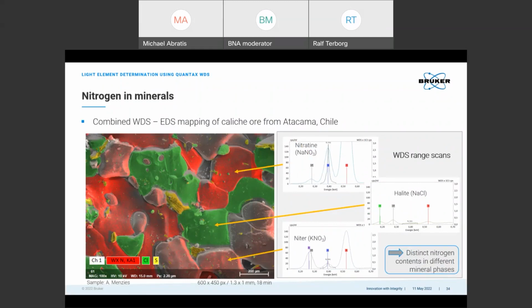There are two principal types of WDS on the market. The classical one uses a so-called Rowland circle and no optic. In such a system, the solid angle is small. That means a lot of the X-rays get lost for analysis. In contrast to that, a parallel beam WDS captures a maximum of X-rays with its optic close to the source of X-ray generation, which means the solid angle is large. And this large solid angle results in a high sensitivity for the low energy X-rays.